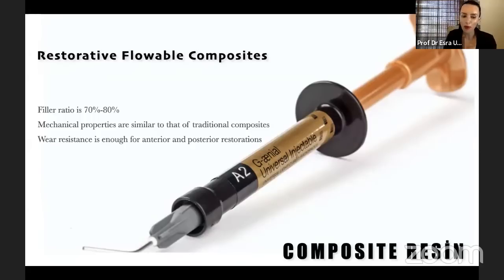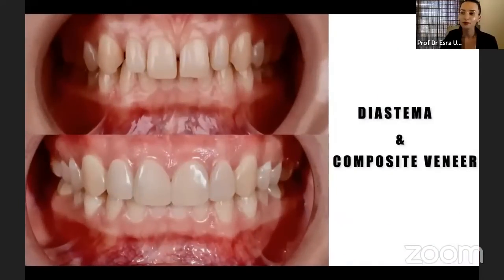Their mechanical properties are similar to that of traditional composite because of the higher filler ratio, and their wear resistance is enough for all anterior and posterior restorations. This is a new era. This material is suitable for all composite restorations in the anterior region. You can use this material for diastema closure, for composite veneers.